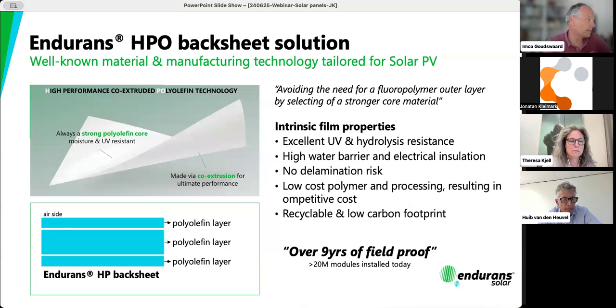This is the solution Endurans offers. What we did is we replaced the weak polyester core layer with a polyolefin layer, and as a consequence, we don't need the fluoro outer layer anymore, because the polyolefin by itself is intrinsically already very stable. And we can use a polyolefin layer on the outside and also on the inside, which gives you a stack which is fully polyolefin based, which also makes it easier to recycle.